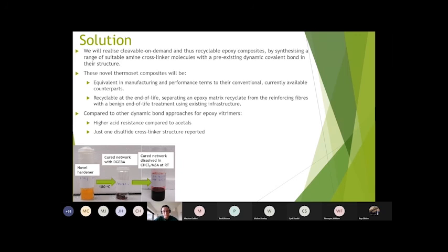It can cure very well with the standard epoxy component, DGEBA, and give us a very nice looking epoxy cured network. And most importantly, this network can actually be dissolved in an appropriate environment, which, as you see there, is a combination of chloroform and methane sulfonic acid, so it is fairly acidic. That can happen at room temperature without any stirring, without any heating, so without any additional energy input.